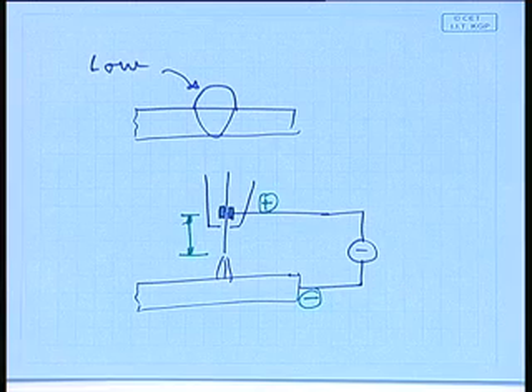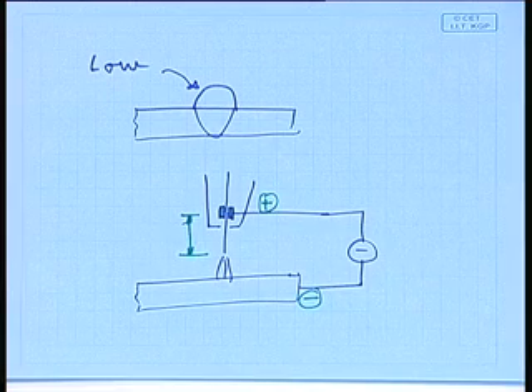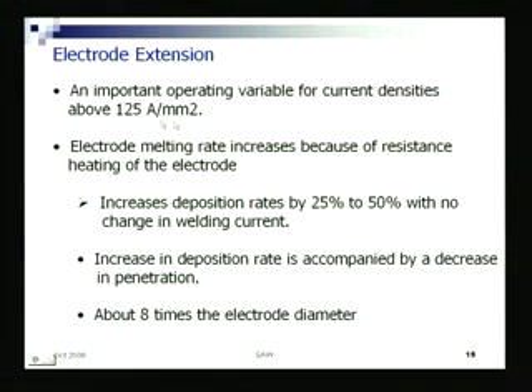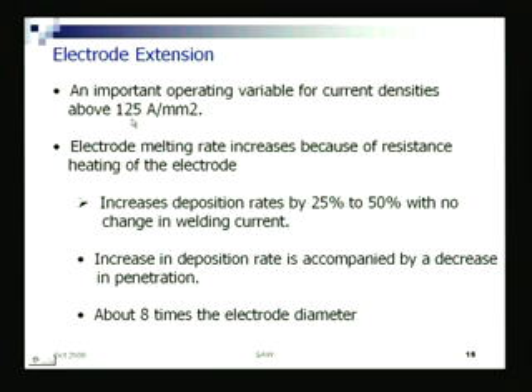But this effect will be more significant provided the current density is above 125 amperes per millimeter square. At lower current levels, increasing electrode extension does not make much difference, but if the current density is above 125 amperes per millimeter square, deposition rates can increase as high as 50% with no change in welding current. That means essentially penetration will decrease, more heat will be generated in the electrode, more power will be consumed in the electrode, thereby more electrode melting will take place.